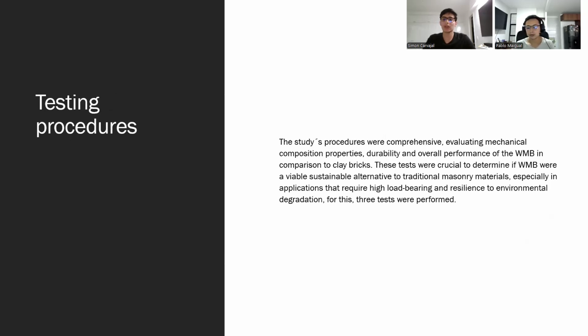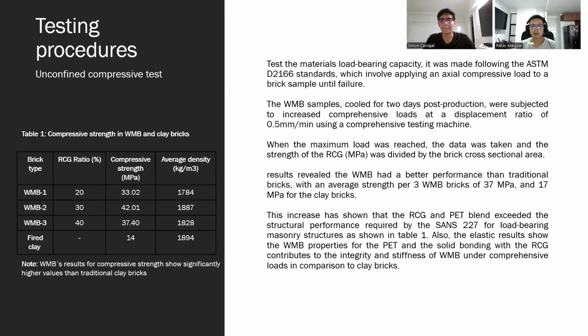Now, for testing procedures, they made various tests, including compressive tests evaluating mechanical properties, durability, and overall performance of the WMB in comparison to the clay bricks. Okay, and the testing produced the unconfined compressive test. The load-bearing capacity is measured following ASTM D2166. The WMB samples, 2 days post-production, were subjected to compressive loads at a displacement rate of 0.5 millimeters per minute. When the maximum load is reached, the data was taken and the strength of the RCG in megapascals was divided by the bricks' cross-section area. The results revealed the WMB had a better performance than traditional bricks.